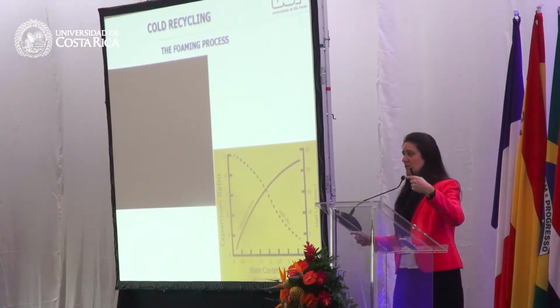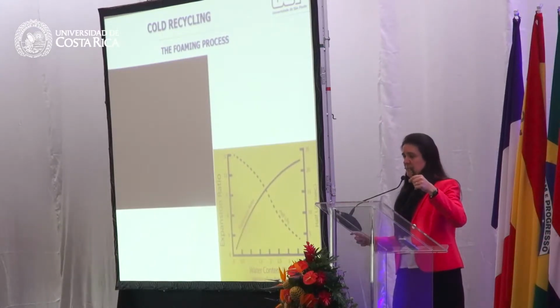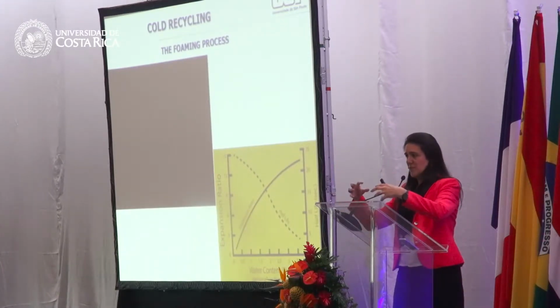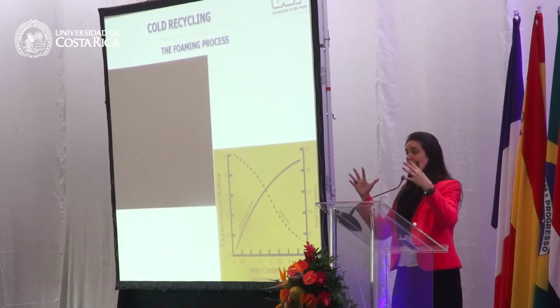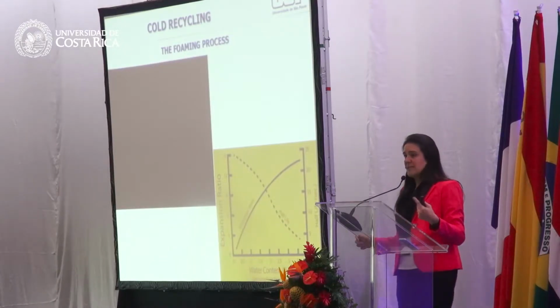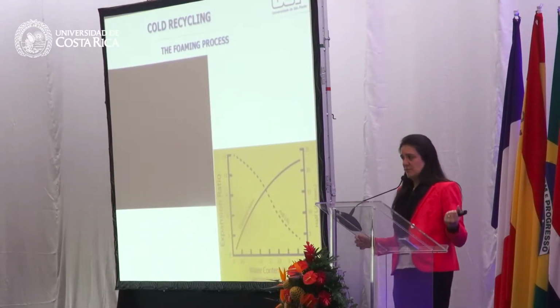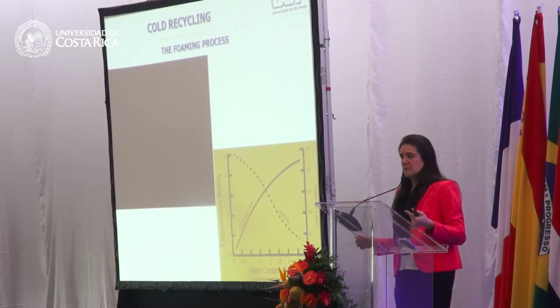You put this hot asphalt binder in contact with water and air. And in this process of mixing all of them, the asphalt binder will try to expand. And it can expand 15 to 20 times the initial volume. So why do I do this process? Why do I do this foaming process?